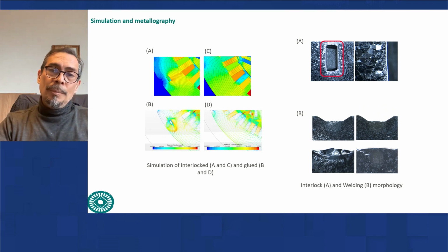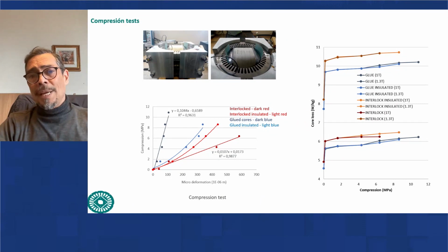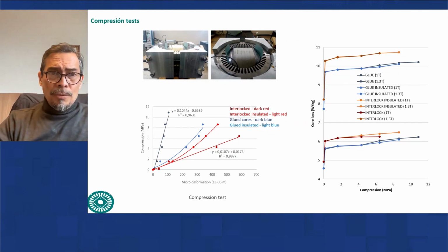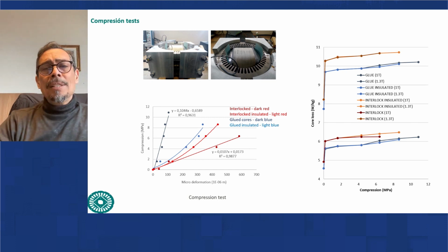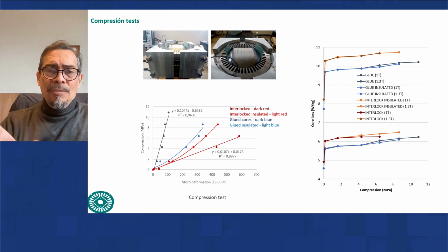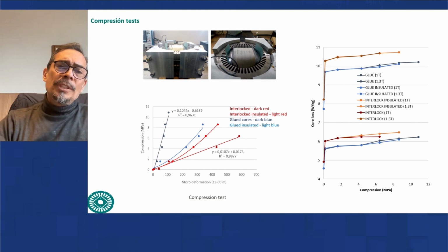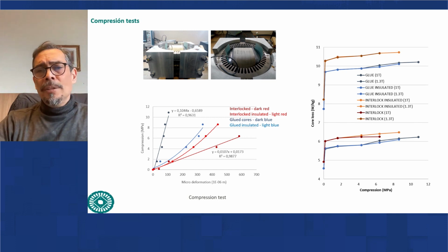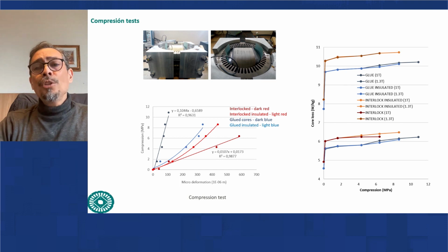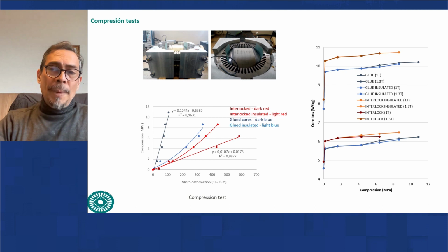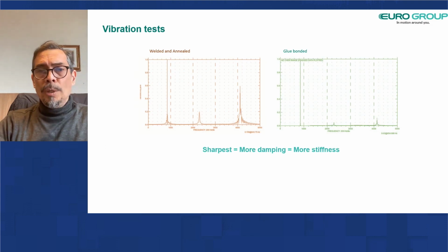As you can see in the metallographic images, these materials break like glass, and once they're broken, their magnetic efficiency is very much diminished. So that is the rationale behind it. But when you continue studying the effect of glue bonding, you can show that the mechanical stiffness under compression, as we replicate the shrink-fitting effect inside of the motor housing, is much better with glue bonding, and the energy losses, even under compression, were shown to be much better when using a glue bonded product. So these are all results that you will be able to find in the communications that I mentioned before.